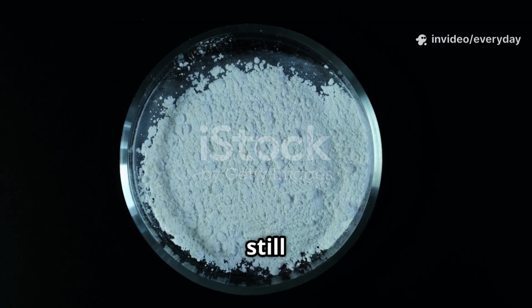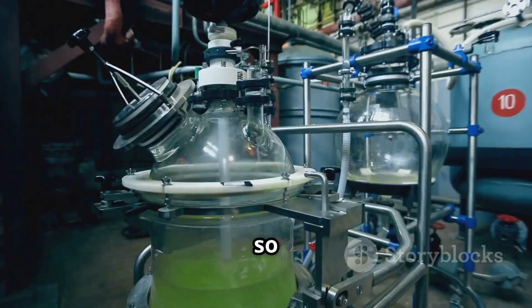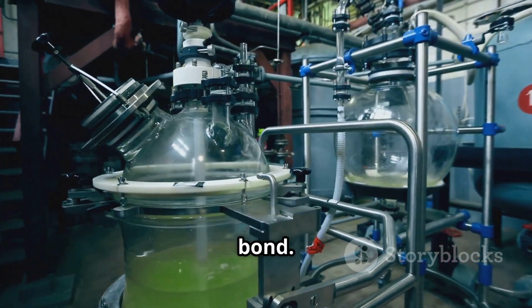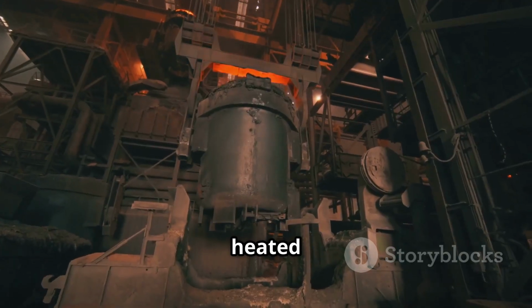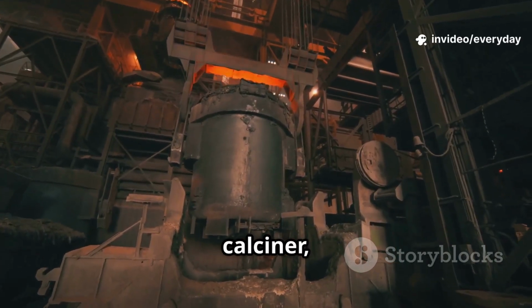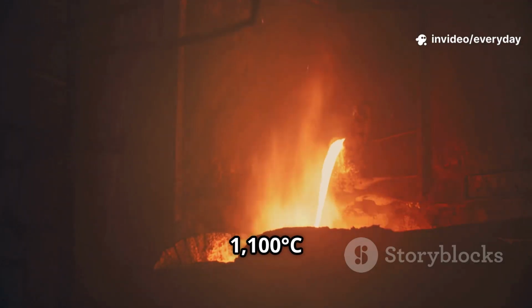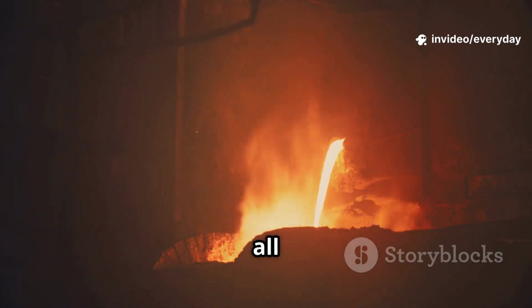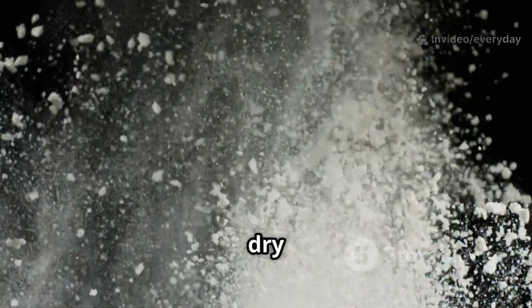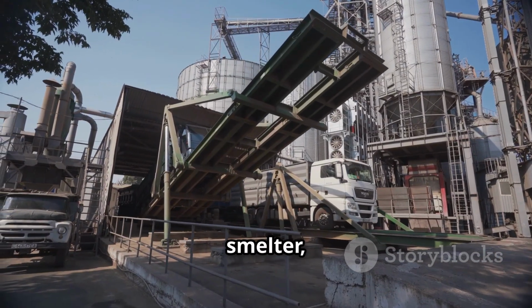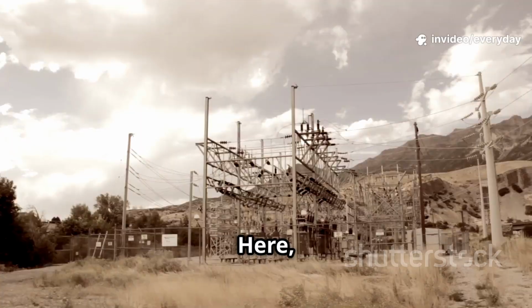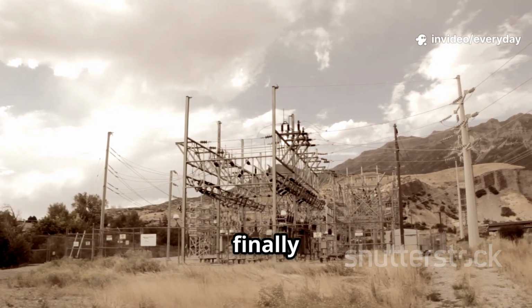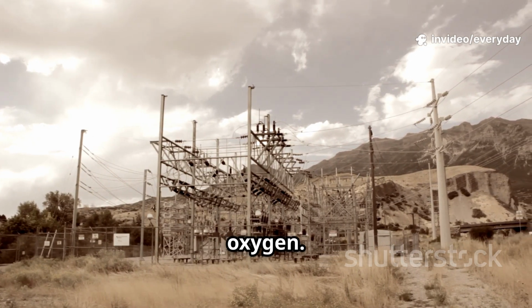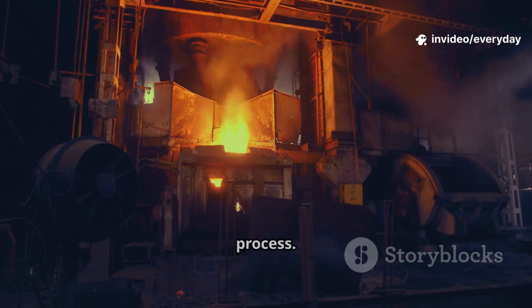The alumina powder still holds tight to its oxygen atoms, so the next step is to break that bond. First, the powder is heated in a giant rotating kiln called a calciner, reaching over 1,100 degrees Celsius to remove all water. This leaves pure, dry alumina, perfect for the next stage. The powder is shipped to a smelter, where the real magic happens. Here, massive amounts of electricity will finally separate aluminum from oxygen. This is the most energy-intensive part of the process.